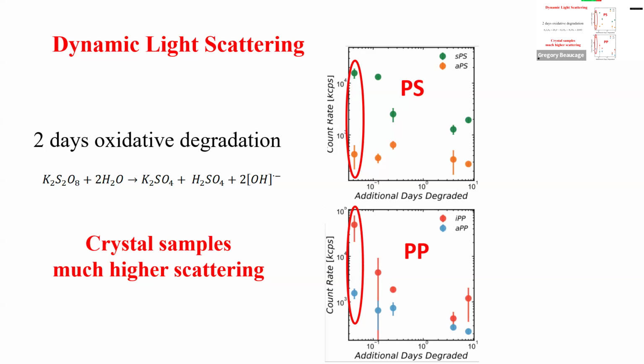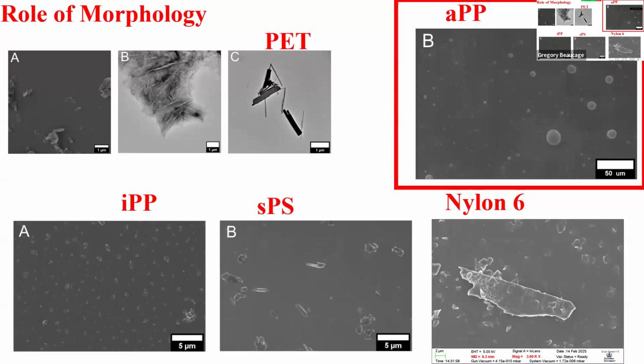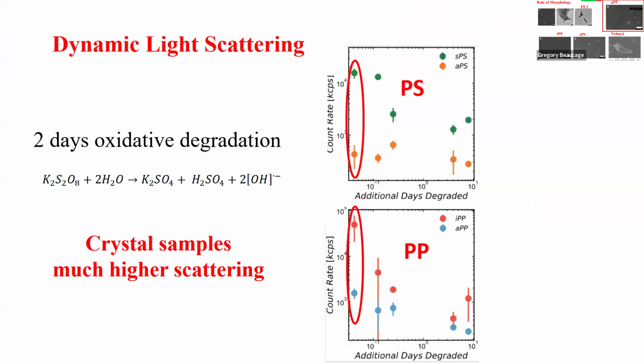Everybody understood that? So the semi-crystalline one does. The problem with dynamic light scattering is, if you look at objects like this, I don't know how to interpret the dynamic light scattering, because the objects are so anisotropic. It's not a sphere. I'll get an effective size, but it has no meaning because these objects are highly anisotropic and also highly polydisperse. That's why I'm not pulling out a size from dynamic light scattering. But I'm going to use this count rate as a metric for what's going on. All right.